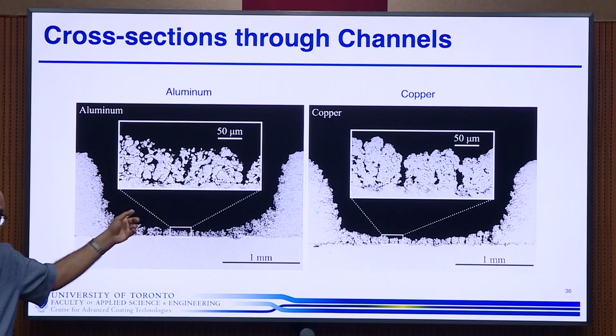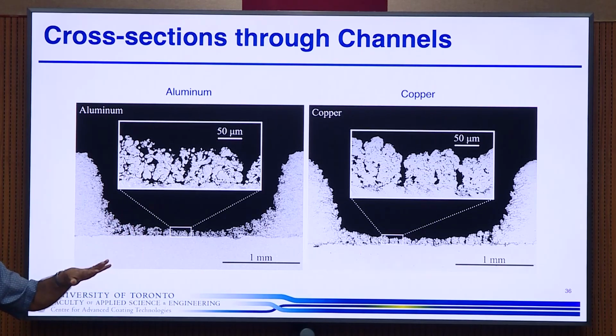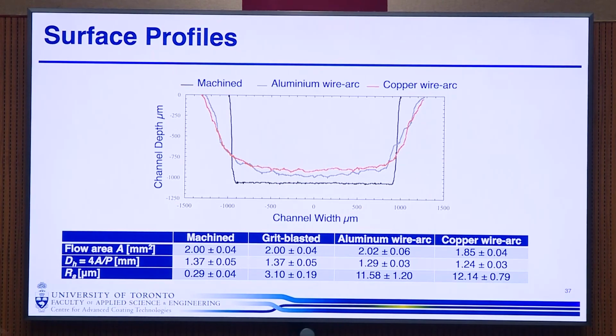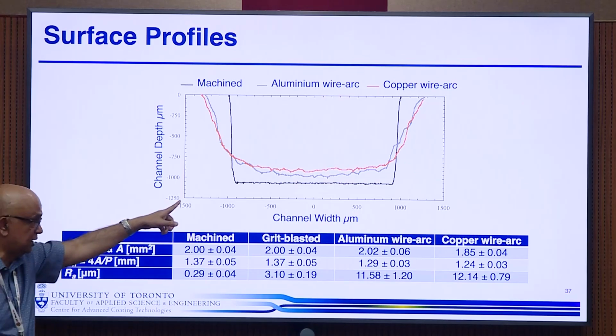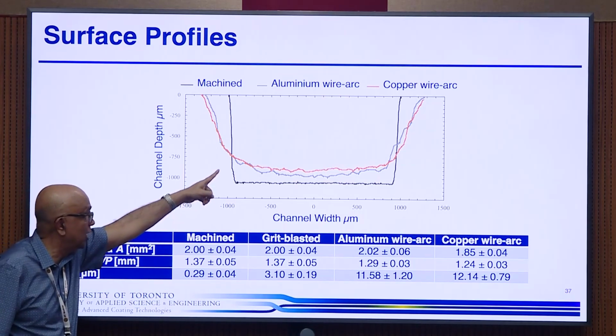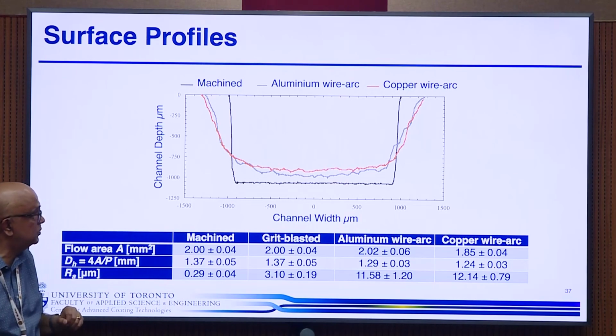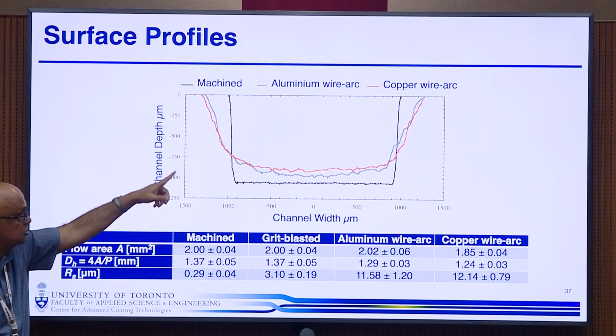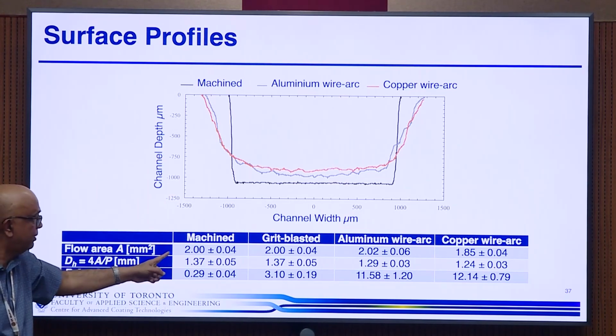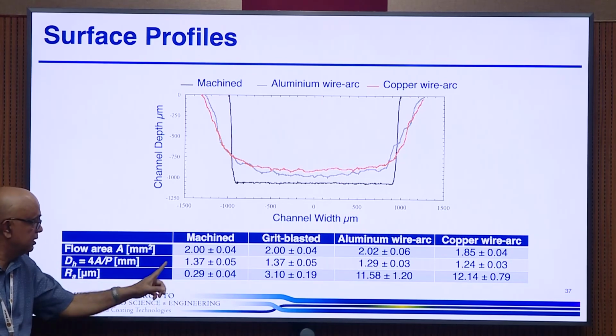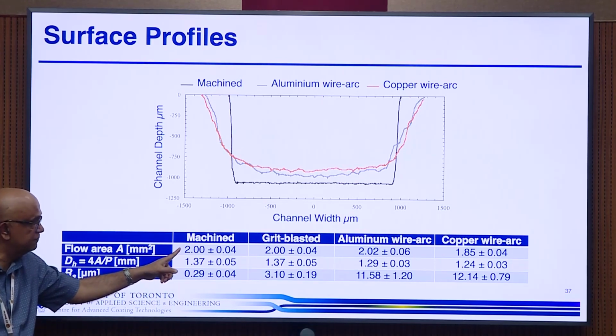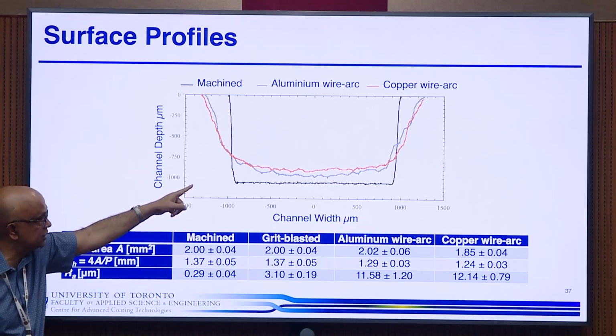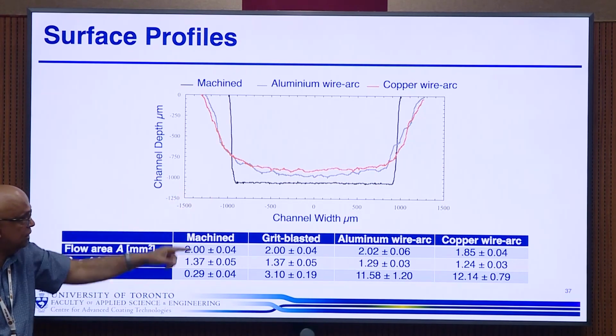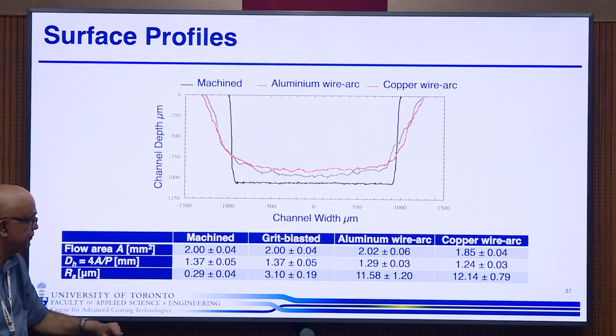This can also, I'll show you, be very hydrophilic as well, especially the aluminum one, if you treat that. So we put it in the surface profiler. We machined one like this out of aluminum. And you can see the black one is the profile of the machined one. The sprayed ones, you don't get such a neat profile, but it's about the same flow area. So we have a flow area of 2 millimeters wide, 1 millimeter high. So it's about a 2 millimeter area.